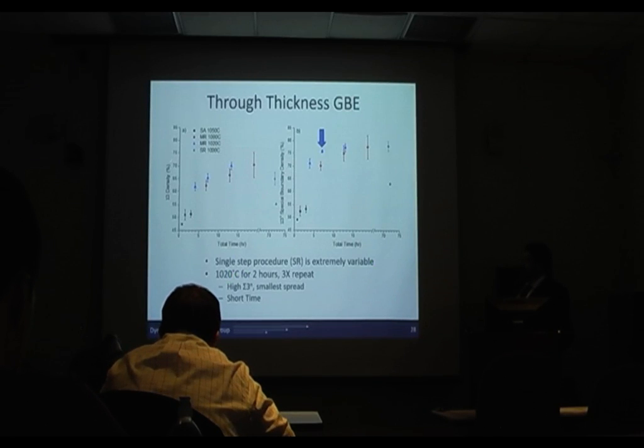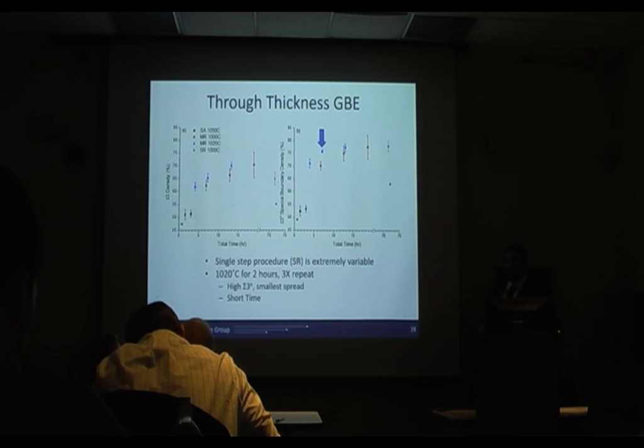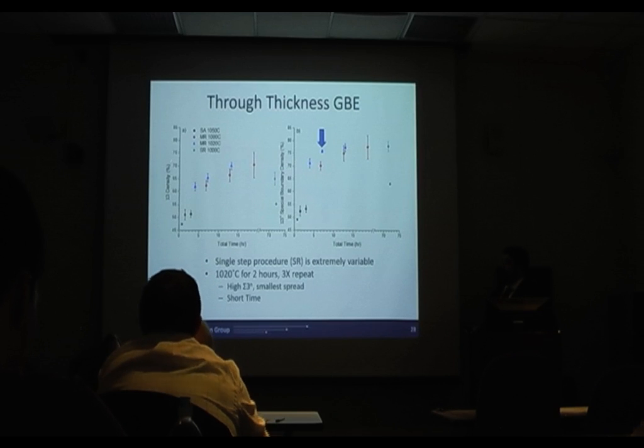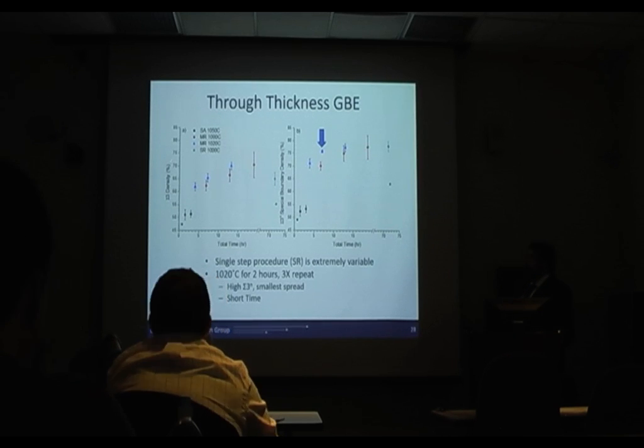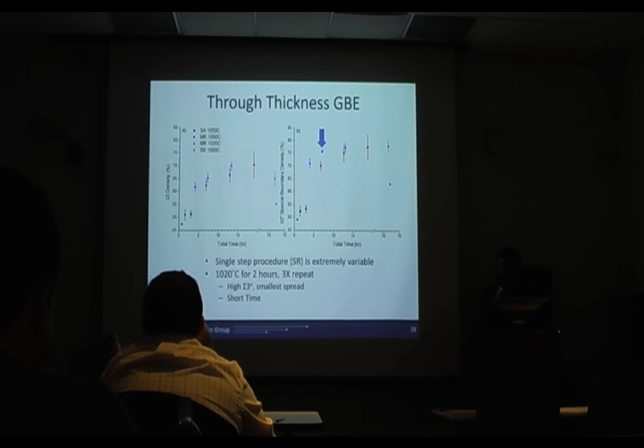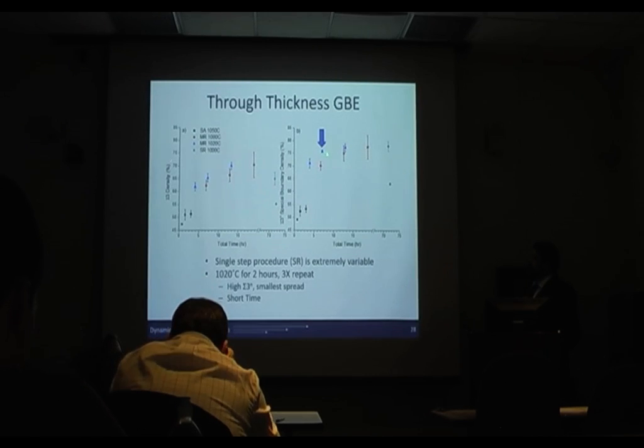So that is referred to here as the SR condition. We went back and we tried several iterated procedures. Again, we're still using 5%, but we tried 3 iterations and then 1000 and 1020 Celsius. And we tried different times as well. And what we found was that our sigma 3 to the n content rapidly reached a relatively high level and was highly consistent, using 2 hours at 1020 C, repeated 3 times with 5% strain.